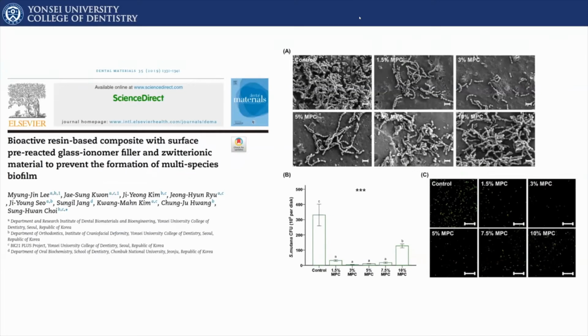So the idea was, just like last time, we incorporated zwitterionic materials into glass ionomers that have a pre-reacted glass, surface pre-reacted glass ionomers, SPRG. The idea was to provide an antibacterial effect and see whether the ionic release from the glass ionomers would be modified by it. As usual, the low doses of 1.5%, 5%, and 7.5% resulted in a reduction of attachment of bacterial colonies, as you can see here. So this is what we already found out from our previous papers.